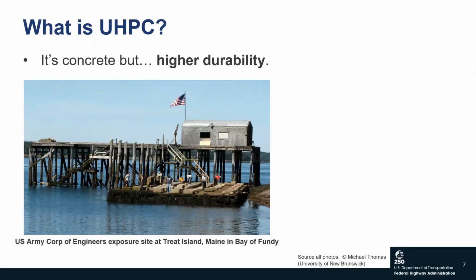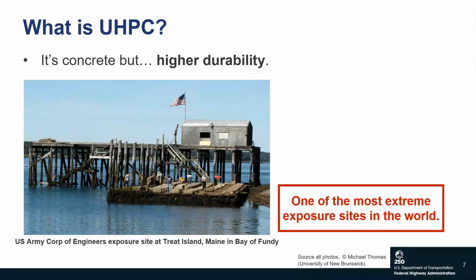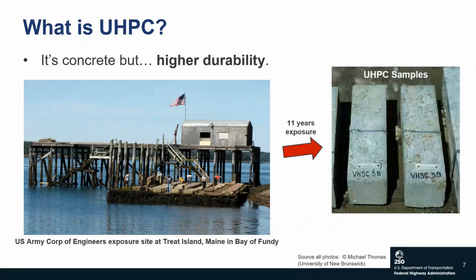So to demonstrate this, what I'm showing here is a U.S. Army Corps of Engineers durability testing facility on Treat Island in Maine, Bay of Fundy. This island is known to have some of the world's largest tides and harshest environment for concrete, with 2 cycles of low and high tide per day, and with potential freezing and unfreezing in cold temperatures. After 11 years of exposure, the UHPC samples had minimum deterioration. You'll see those brown spots there. Those are local corrosion of fibers that went away, but it's cosmetic.